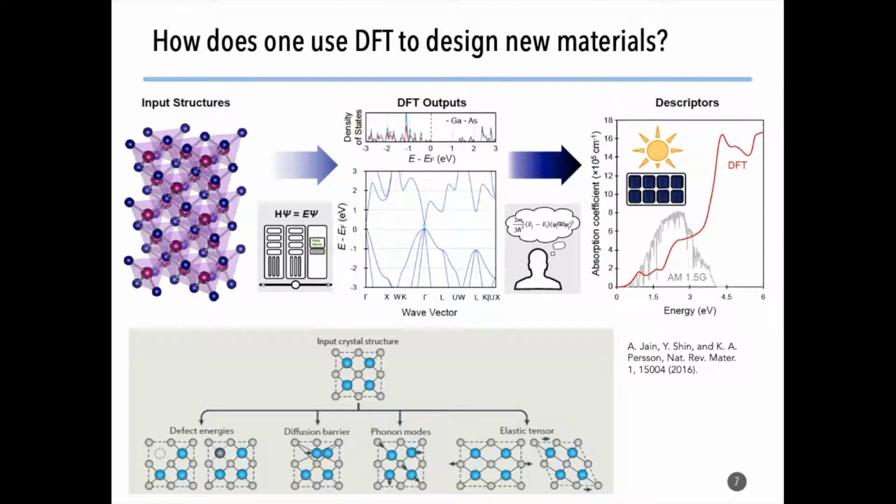If you're unfamiliar with density functional theory, in practice, the way that it works is that you define your material system. So these are atoms in a repeating cell with periodic boundary conditions. And you can have different atoms at different locations that describe the material that you're interested in. And then you apply some computational power to actually solve these DFT equations. And you get back fundamental properties of this material. So this is the electronic band structure of the material. And then you can do further processing on these fundamental properties to get technological properties of your material.